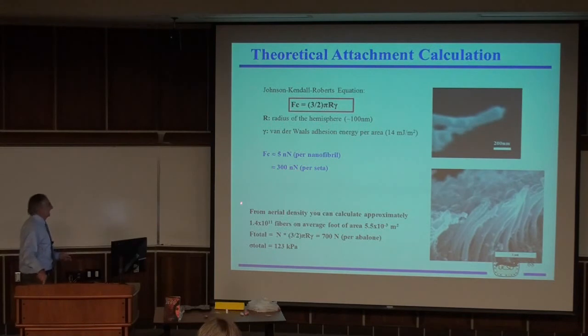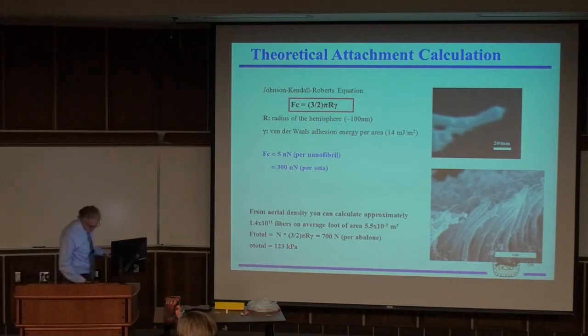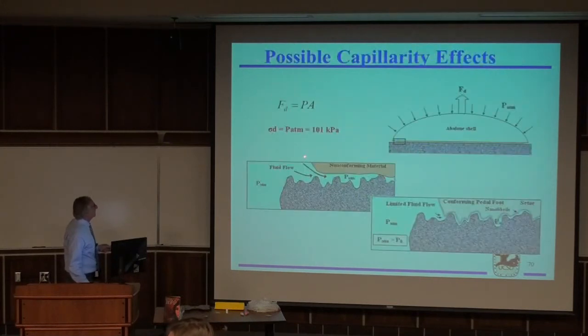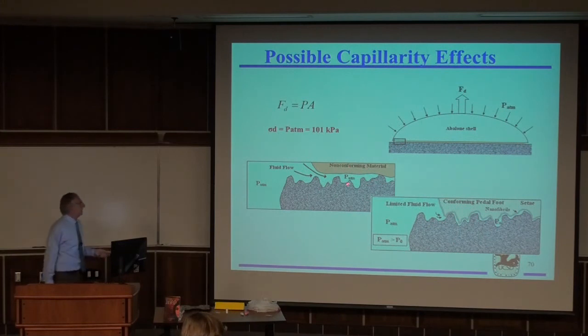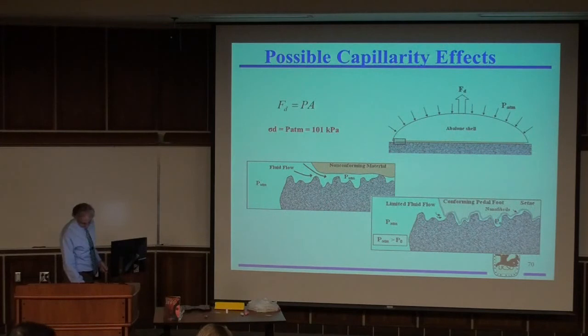Okay? And then we crank it out, and we calculate the total stress per abalone is about 123 kilopascals. And that's very close to the measured value of 110. So this could explain it. However, what I think is that these nanofibers close all the gaps, and they conform very closely to the pebble surface, so the water cannot get in. If the water cannot get in, then you have the forces of the hydrostatic pressure that you have to overcome. The force has to be equal to the hydrostatic pressure, and it can conform to many substrates.